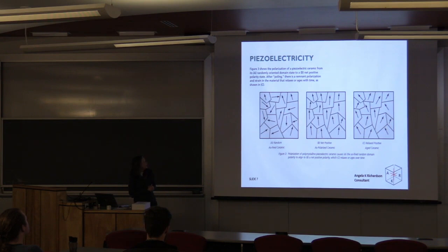The aging process is when that ceramic starts to, over time, logarithmically, relax. What happens is that those domains start to want to go back to their original random configuration. And that happens, like I said, logarithmically. So the first 10 days, you may have a certain percent. Then the next 10 to 100 days, the same percent, and so on.